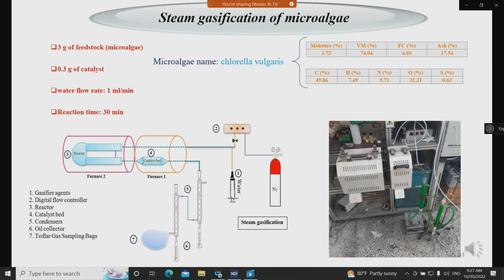According to proximate analysis, the ash content of microalgae is more than that of other common biomass feedstocks for gasification. Although the high content of ash can play a catalytic role in gasification processes, ash content can also stimulate coke formation and induce reverse water gas reactions. Therefore, this necessitates the significance of applying perovskite supported catalyst for their resistance against carbon deposition.